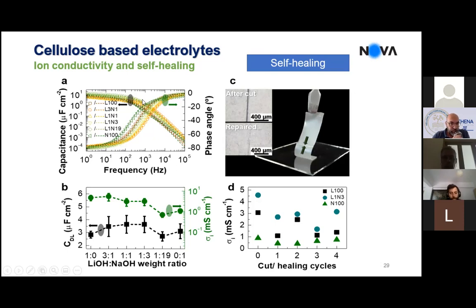That is, you have a limitation on the maximum frequency that these devices can operate, because this capacitive behavior, or the formation of the electrical double layers that you get using these electrolytes, is only possible below 1 kilohertz or something like that. So you see here the impedance measurements, and see that the transition between the capacitive and the resistive regime, that is when the phase angle goes below -45, is around 1 kilohertz. Okay, so it's basically in principle the maximum operation frequency where we can extend this type of transistors, and this is indeed a limitation for this type of approach using electrolyte gated transistors. There are some electrolytes where you can extend a little bit more in terms of frequency, because you can tune the ionic conductivity and ionic mobility in the electrolytes, but for solid state electrolytes it will be somewhere around these values.